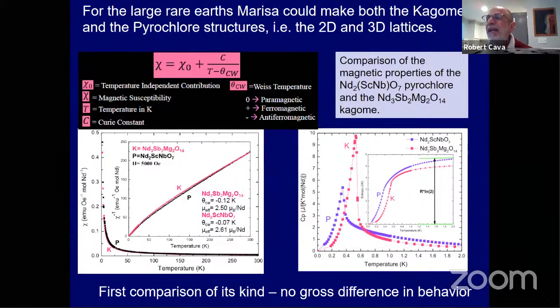You can make both of them, and you can make them both pure, and you can plot on a single curve the magnetic susceptibility versus temperature, which is shown on the left side here for these two things. And as usual, you see a very low interaction temperature, a fraction of a Kelvin, which is not good. We'll see more about that later. And the magnetic moments are very similar.